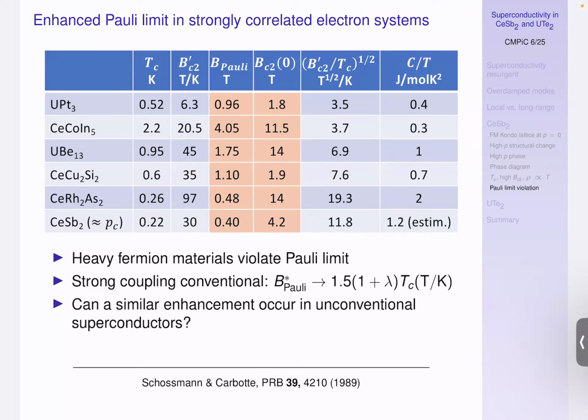But it could easily be, right? I'm not saying that all of these are necessarily singlet superconductors. All I'm saying is it's quite common for heavy fermion superconductors to break through the Pauli limit. Now, I think in UTe2 there's a lot of very convincing evidence from NMR that it's actually a triplet superconductor. So I suspect that really is a triplet superconductor. Whether the cerium-based ones are triplet is less convincing.